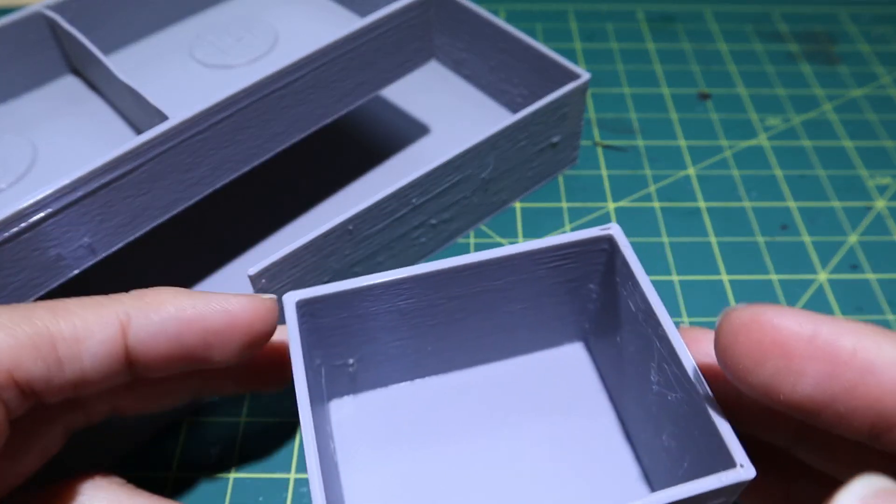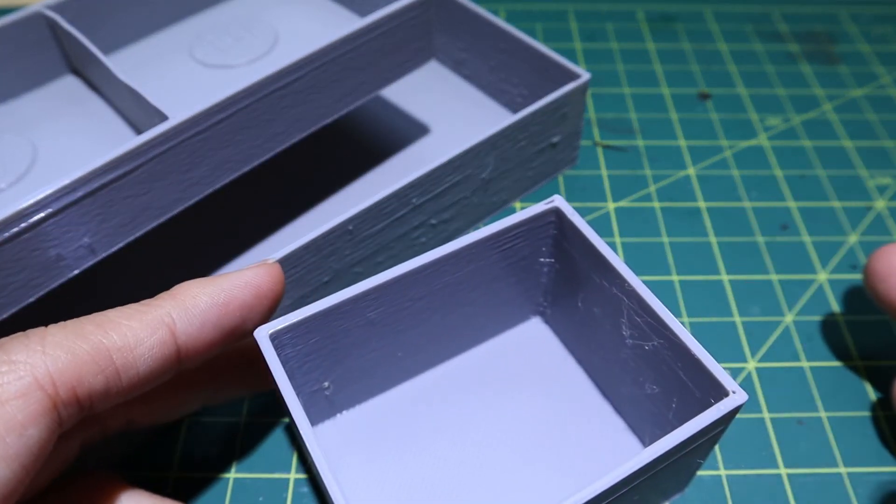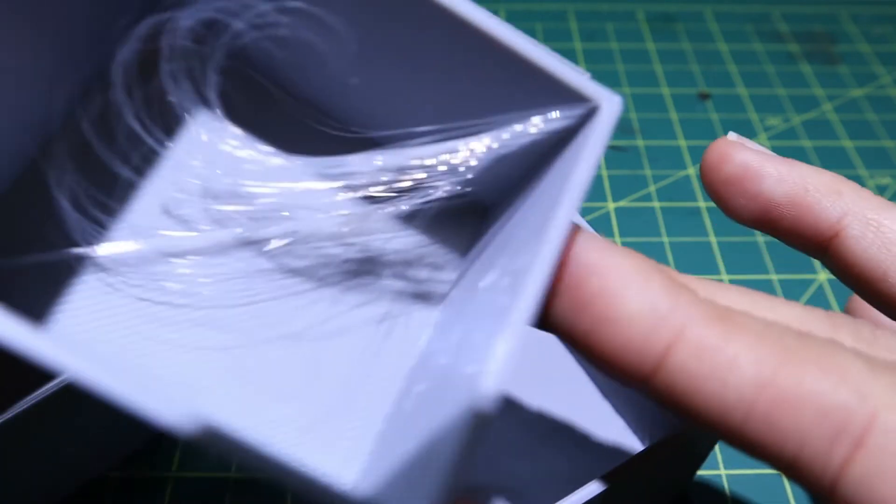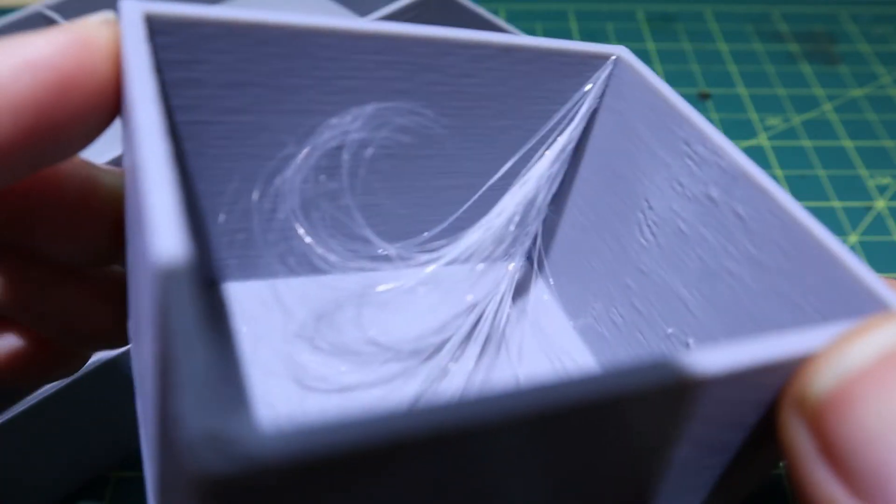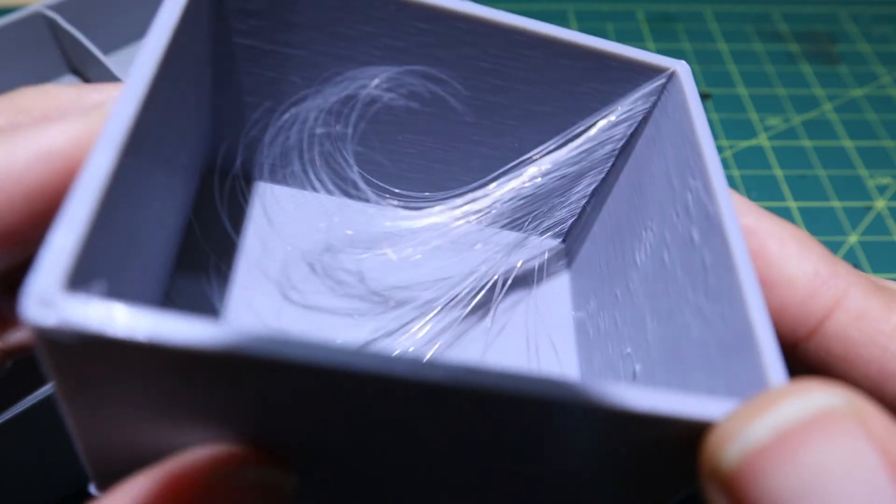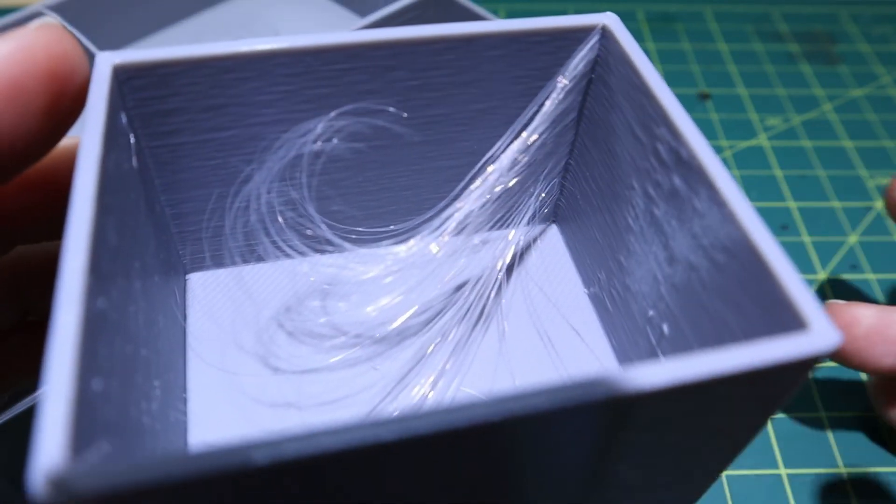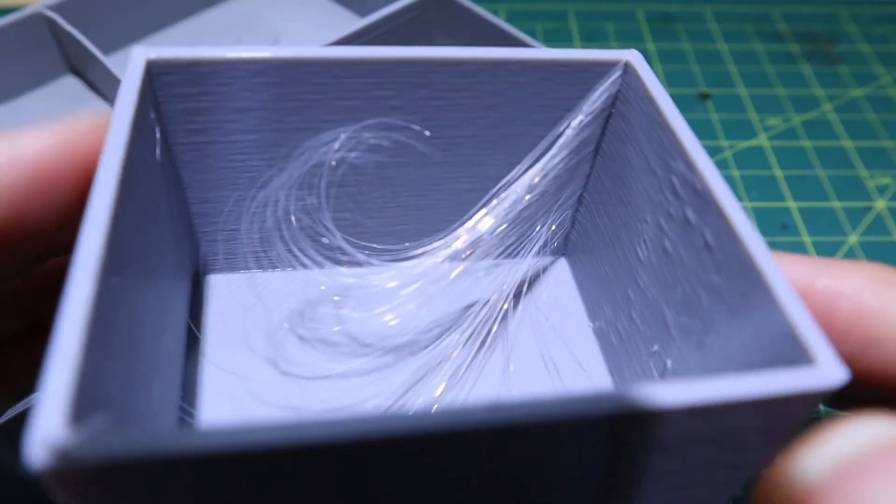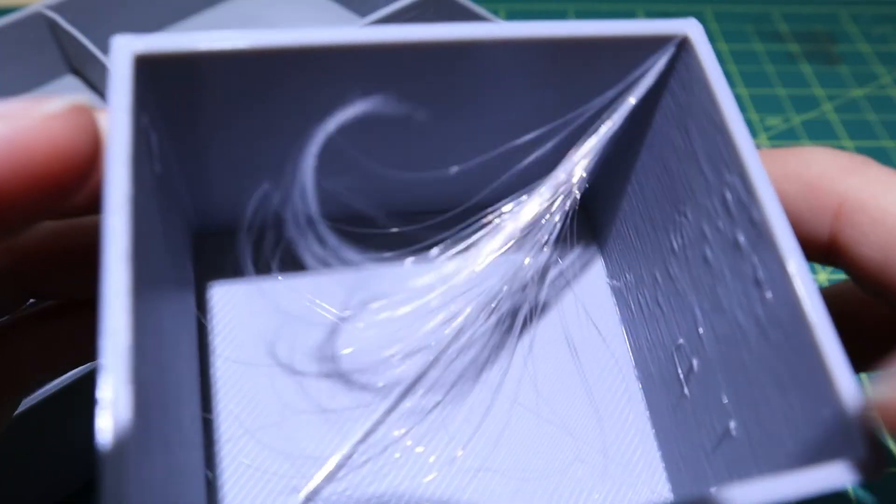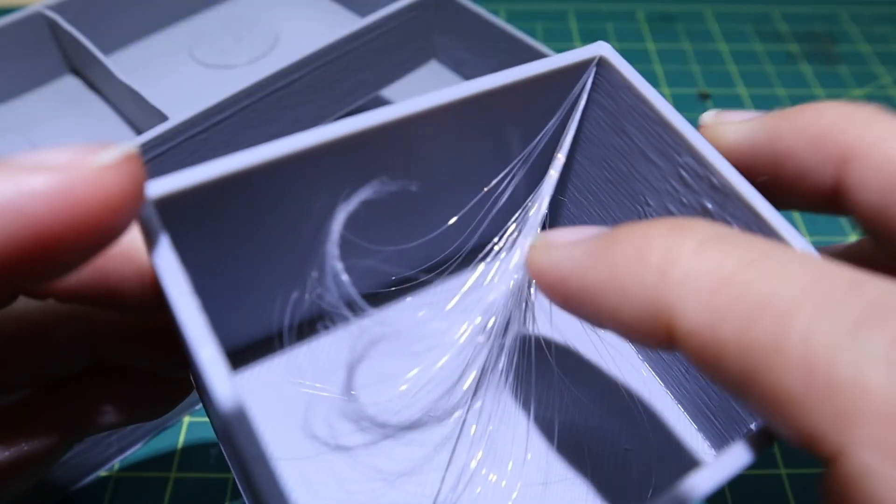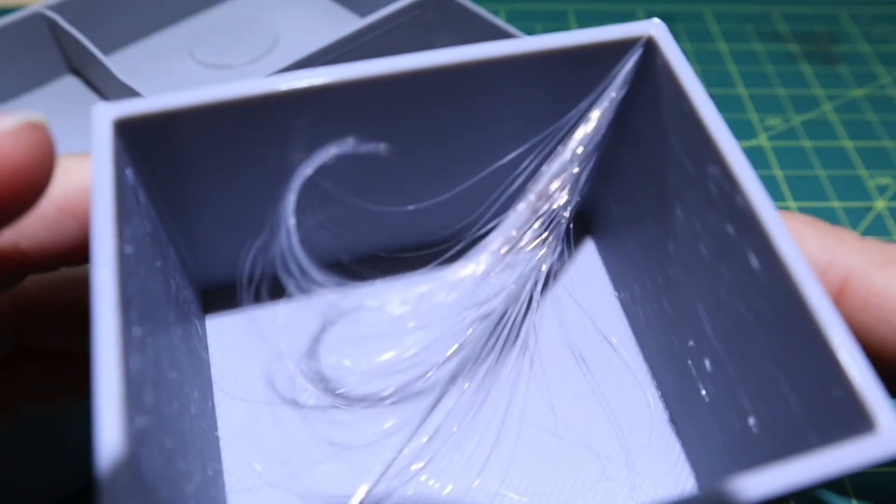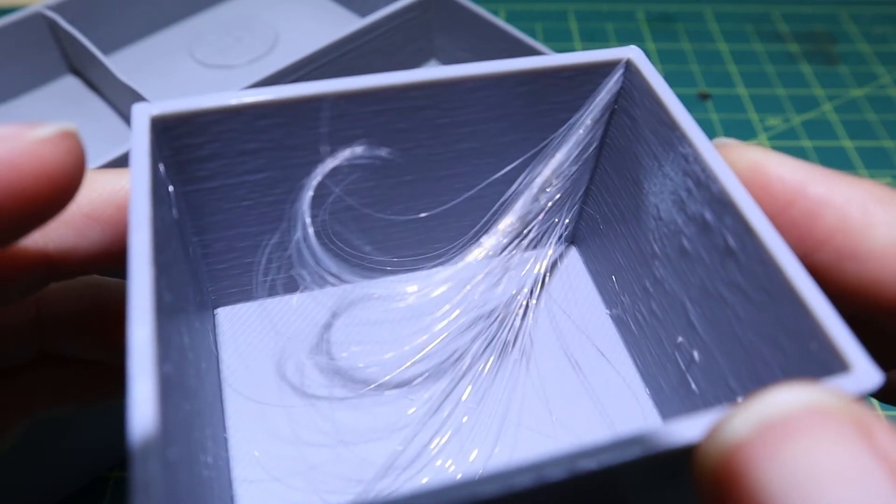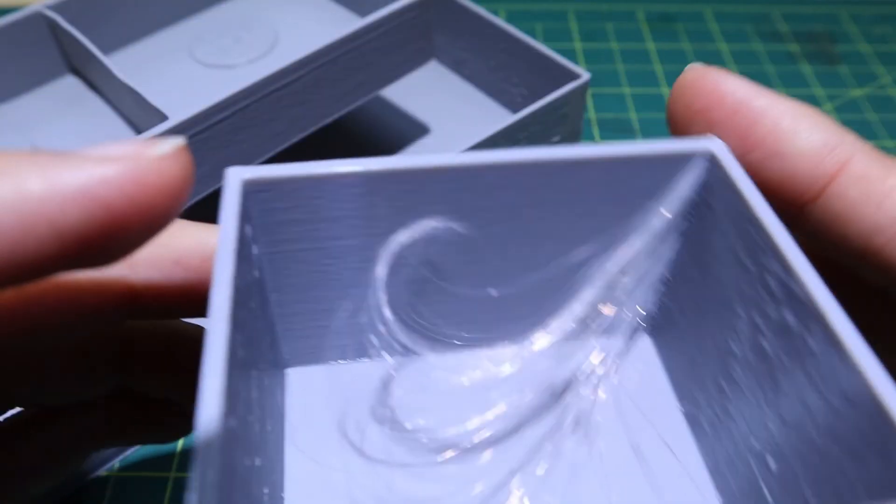And here is the result. The piece that I printed with the retraction set to 0 - without retraction you will have a lot of stringing, but this is easier to fix with the hot gun. So I'd rather deal with the stringing problem than having a piece that's easy to break right at this corner.